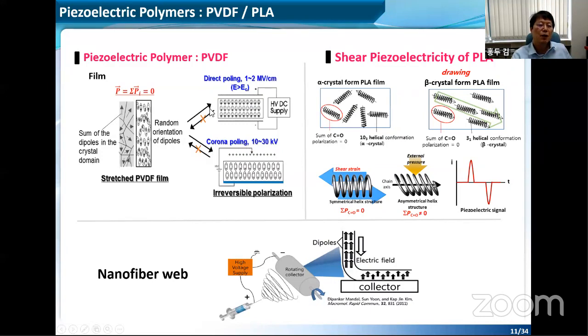In the case of polylactic acid, it's not like PVDF. It has a helical conformation. Normally the alpha crystal has a 10/3 helical conformation. But in this case, even though we apply some external force, it doesn't give us a dipole moment change. But once we draw it, it becomes the beta crystal, called the 3/1 helical conformation. In that case, if we press it, it gives us some shear piezoelectricity.